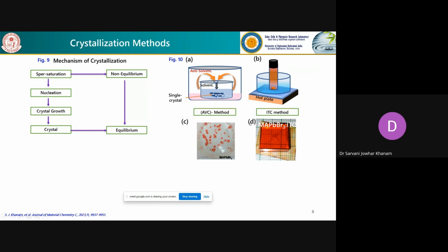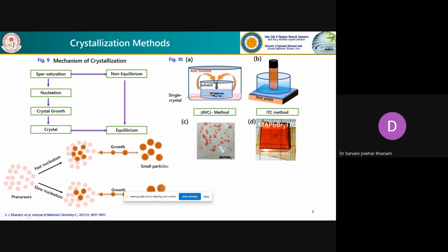Here D in figure 10 indicates the crystals which we have grown in our lab on the ITO, which is 1.4 centimeter in length, and the thickness of this material is 0.6. This is suitable for higher energy radiation detection, which we have successfully done for the DRDO project. Coming to nucleation, there are two processes, fast nucleation and slow nucleation. Depending on the size of the particle, if we want larger size crystals, we need to go for slow nucleation, where temperature plays a major role.